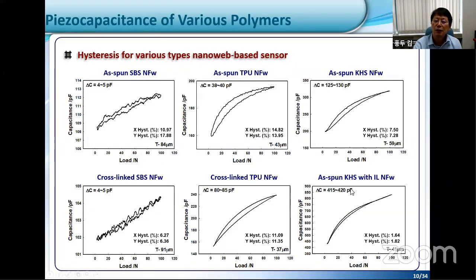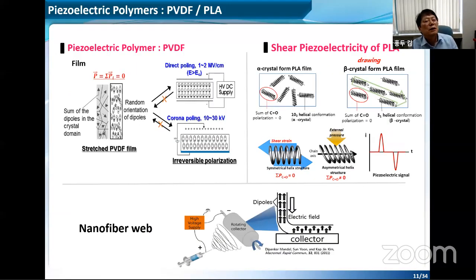And as I told you before, KHS is a very good material. With a small amount of added ionic liquid, the capacitance change is almost 400 picofarad. Also, the hysteresis goes below 2%. It is the world's best material in terms of hysteresis. So at least we know we have a very good piezocapacitive material, KHS, with a small amount of ionic liquid. In some cases, we don't need this ionic liquid. And then let's move on to piezoelectric materials.